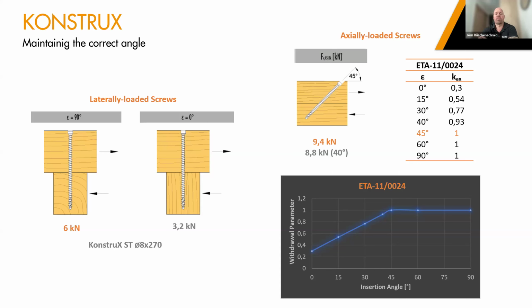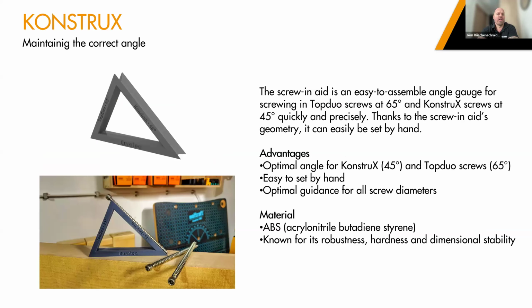But to hold on to this, it's quite important that the workers on site know how to maintain it. When I was still working on site, we built ourselves jigs: just cut some MDF, cut some ply, get a 45-degree ramp just to have the screws at an angle. So we tried to take this pain away from the workers by making a simple jig, which is simply a plastic part, a simple angle template. We made a simple plastic part which is 45 degrees on one side and 65 on the other side. And also there, the drill point tip comes into play.